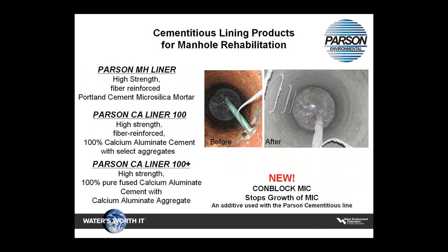Parson CA Liner 100 is a calcium aluminate cement-based lining product for use in lower pH, higher corrosive environments. Parson CA Liner 100 Plus combines calcium aluminate cement with calcium aluminate aggregate to provide an even higher level of protection. Conblock MIC is a liquid additive used with either MH Liner or CA Liner 100 to eliminate microbial-induced corrosion, which is the primary cause of deterioration in manholes. It basically removes the food source for the bacteria, thereby starving them.